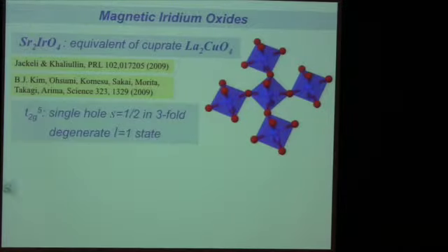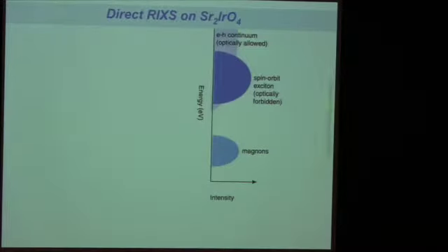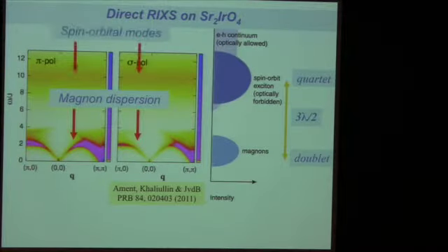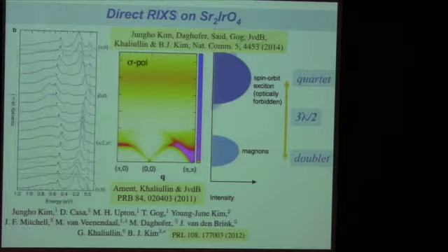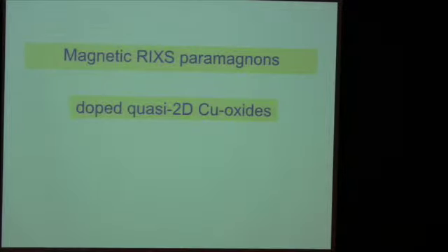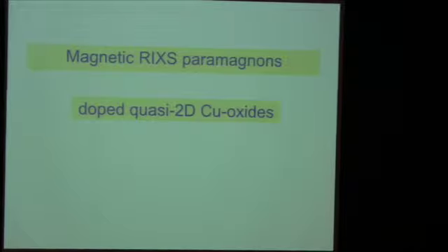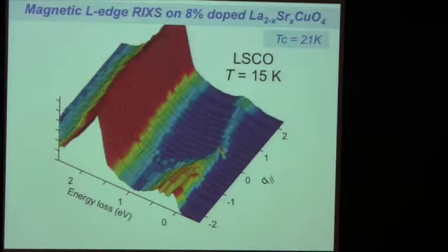Okay, let's not go through that now, and just finish with the open problem, which is the doped cuprates. I'll just show you the data and then leave it at that. So, magnetic RIXS paramagnons, which is relevant for doped quasi-two-dimensional copper oxides. This is one of the first spectra taken, again by the Milano group. It's on 8% doped lanthanum strontium copper oxide. 8% LSCO has a Tc of 21 Kelvin. These measurements were done just below Tc.